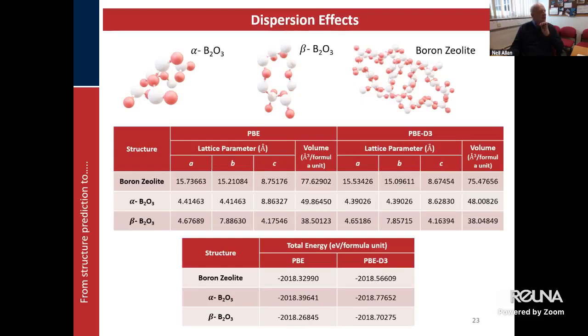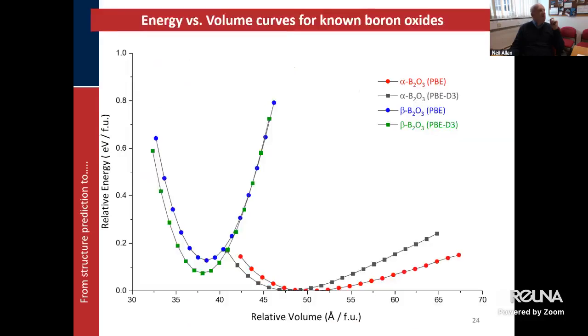And the conclusion is that the boron zeolite structure, whose formula is B2O3 again, is not that much higher in energy than the known structures of boron oxide. Here are some of the energy versus volume curves for the known forms of boron oxide, with and without the dispersion corrections. The curves become slightly narrower when you include the effects of dispersion.